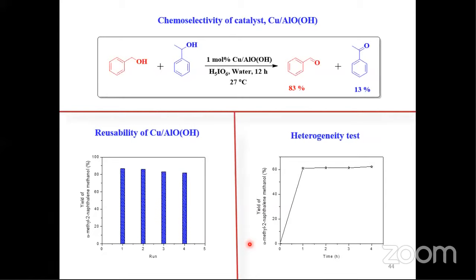And again, to establish the selectivity of the system, we have taken an equal amount of primary alcohol and secondary alcohol. We have seen which alcohol is preferentially oxidized in the presence of this copper and boehmite catalyst. If you look at the product, the oxidation of benzyl alcohol into benzaldehyde happens predominantly in the presence of this catalyst, right? So we have obtained 83% of this benzaldehyde. Only 13% of acetophenone was formed from this 1-phenylethanol. It means if we have primary and secondary alcoholic groups in a substrate, this catalyst prefers to oxidize the primary alcoholic group to the corresponding carbonyl compound. So that is the selectivity, right?